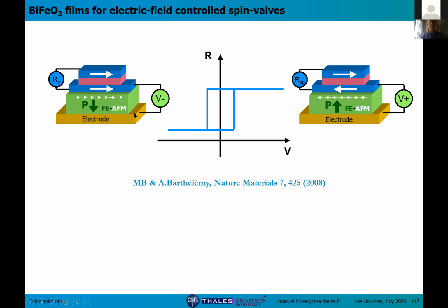As I told you, there are very few ferromagnetic ferroelectrics. If we had a ferromagnetic ferroelectric at room temperature, it would be much easier, but we don't. So this is basically going to work with bismuth ferrite, for instance. Bismuth ferrite is probably the only room temperature multiferroic. So basically the device works as follows. You have a coupling between the polarization and the spins in the multiferroic.